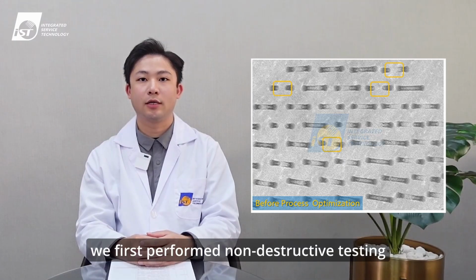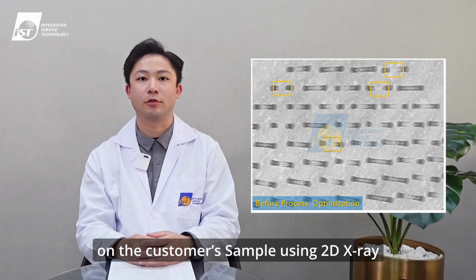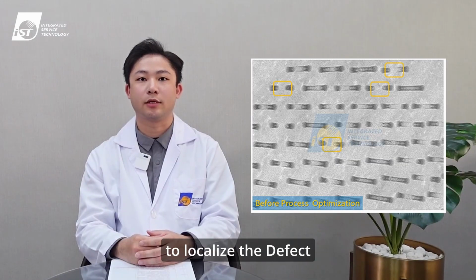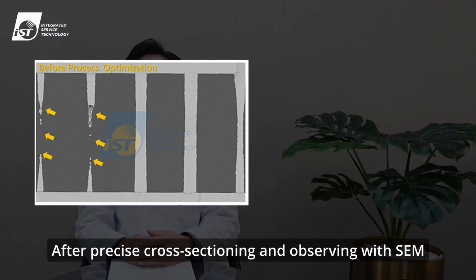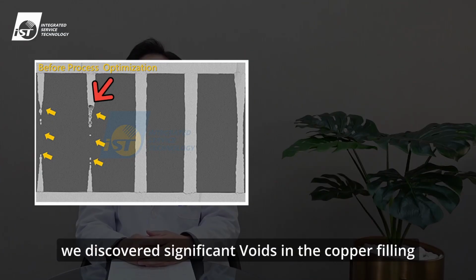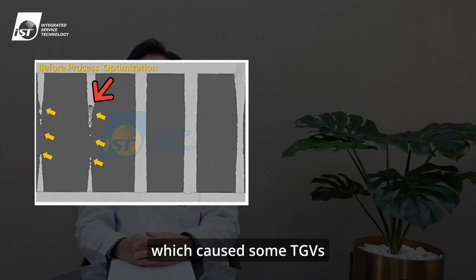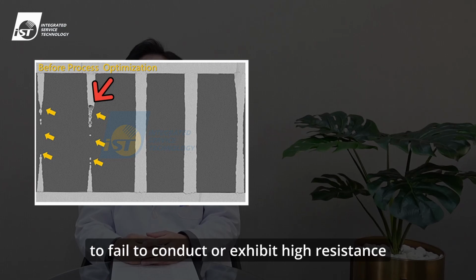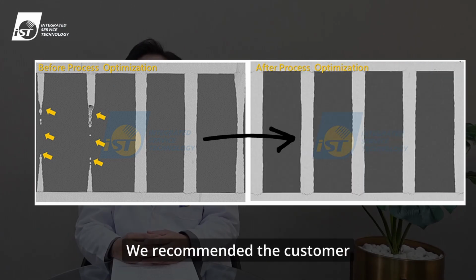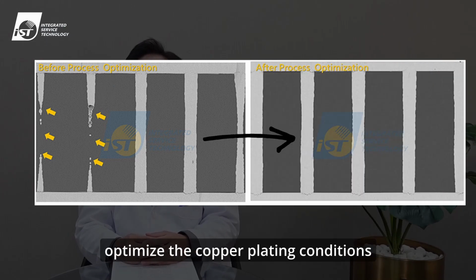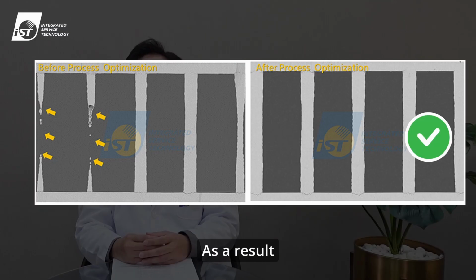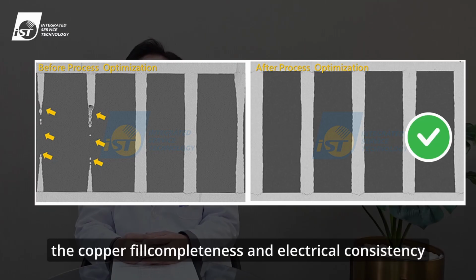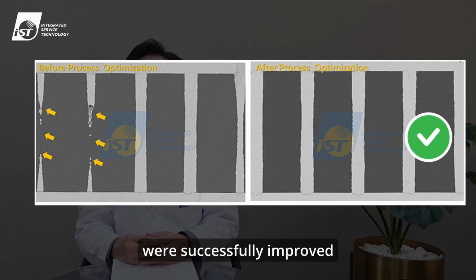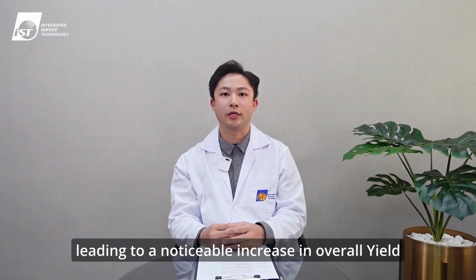In this case, we first performed non-destructive testing on the customer's sample using 2D X-ray to localize the defect. After precise cross-sectioning and observing with SEM, we discovered significant voids in the copper filling, which caused some TGVs to fail to conduct or exhibit high resistance. We recommended the customer optimize the copper plating conditions by adjusting the plating time. As a result, the copper fill completeness and electrical consistency were successfully improved, leading to a noticeable increase in overall yield.